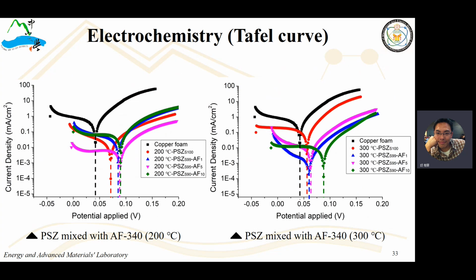And I'll show you this anti-corrosion effect. Okay, so this black one shows the pure copper foam. And for this region, it shows the polysilazane pre-ceramic precursor incorporating the fluorinated resin AF-340 with different compositions. So what do we get?